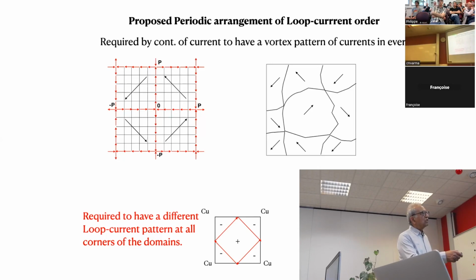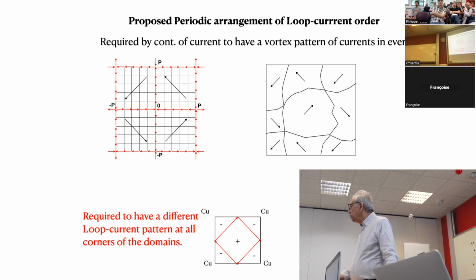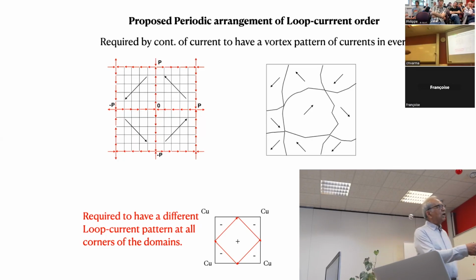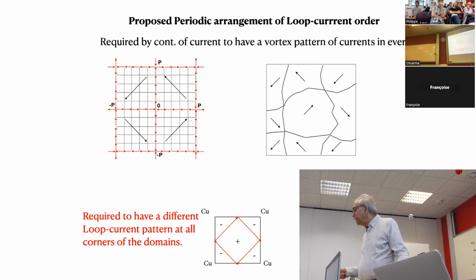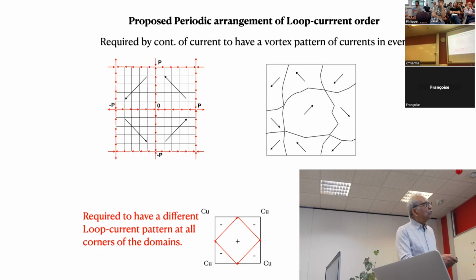And I never bothered about it, but this was only a point, and I expected this P to be from 8 to 10, the period to be at least 8 to 10 unit cells. Okay? Now, the interesting thing about the topological aspect of it is, because these materials are dirty, they're not so very clean, especially in the pseudo-gap phase. But if I go from something like that, this property that there will be vorticity around here, here, and in fact, there'll be vortex-like feature at these, all the corners, has to be preserved current conservation.